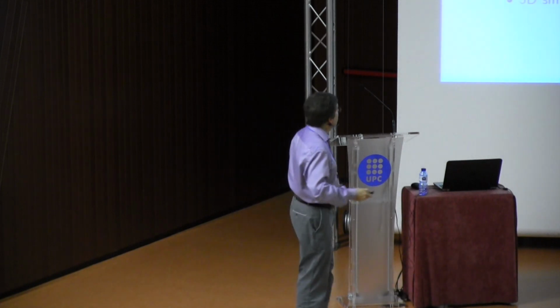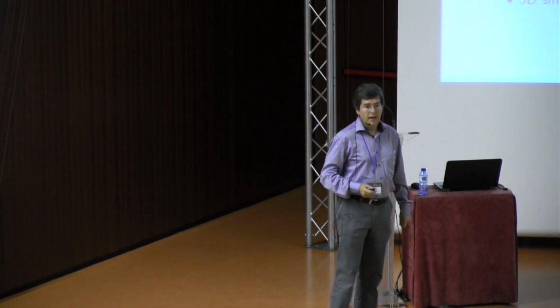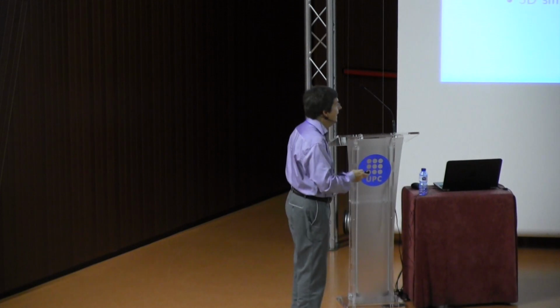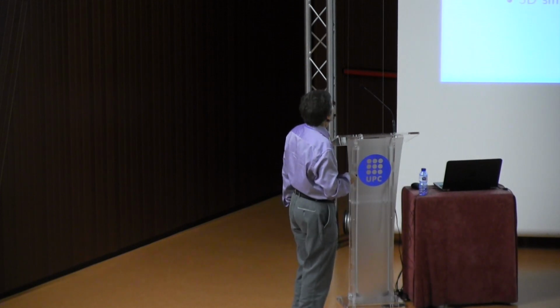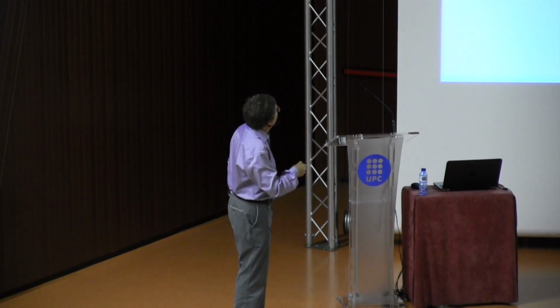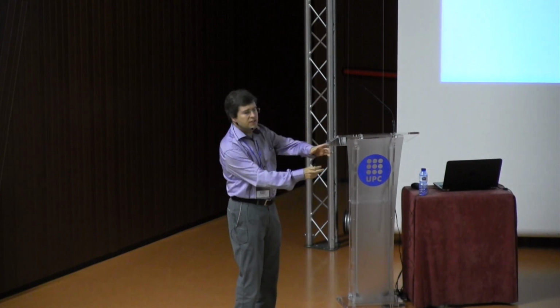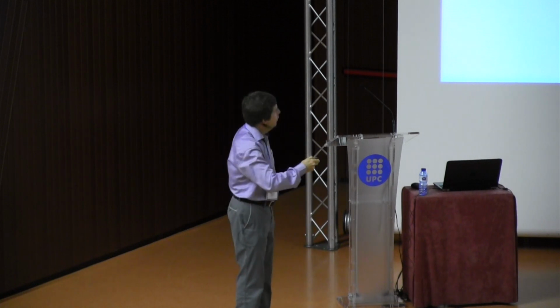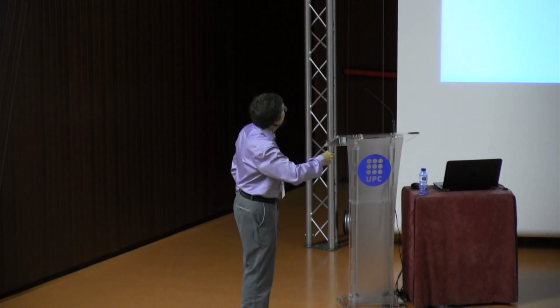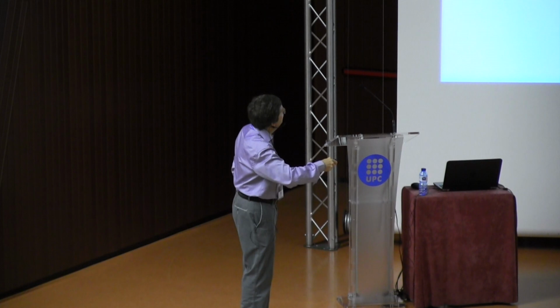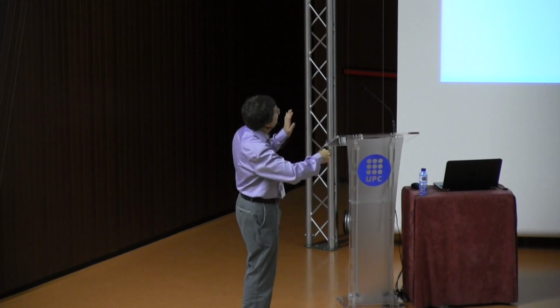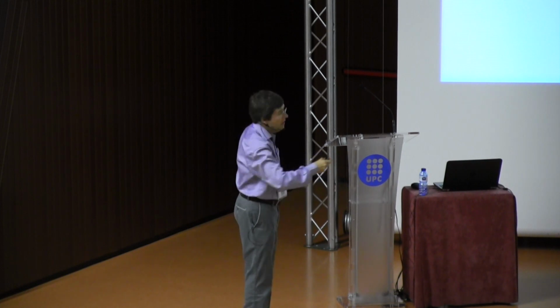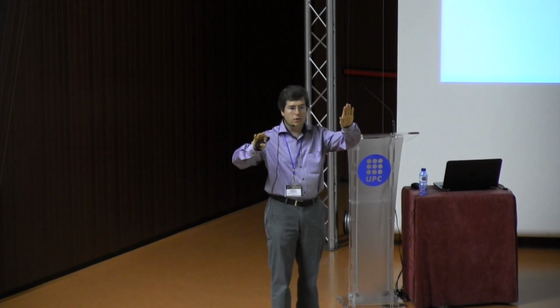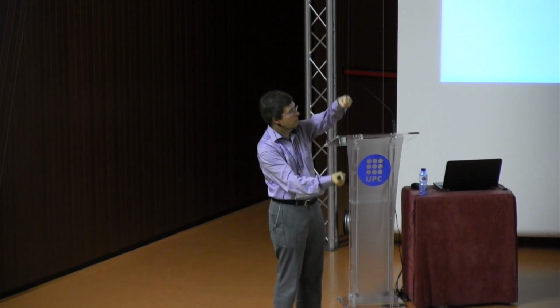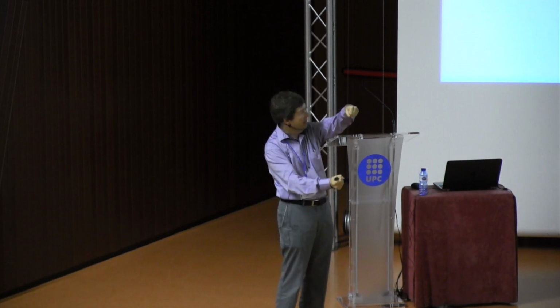But what we need for these single crystals are 3D simulations. And there, since I am already late, I will show you only two pictures. What you see here is a crack. You have to imagine a sample with a flat surface. You have an initial crack, which is black here. So you see the crack front, the initial crack front at the free surface. And what you see here are the propagation of the crack front, while the sample was subjected to cyclic loading.